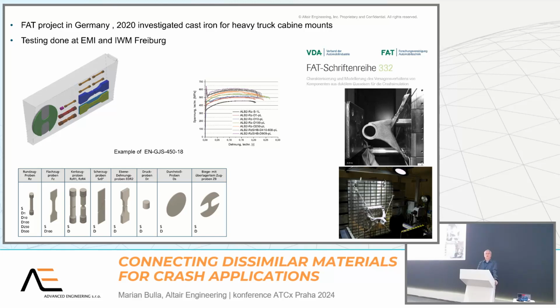For the material cards, just different velocities from a tensile test were used here. Here, strain rate dependence on metals in this case was obtained. For polymers, it's even more valid because polymers are definitely highly affected by viscosity, which means different loading velocity. For metals, it depends. You cannot see it on the metal, you have to test it. Some metals are highly strain rate affected, some are not, or do not show it too much. Which one is which? I don't know. It must be tested.